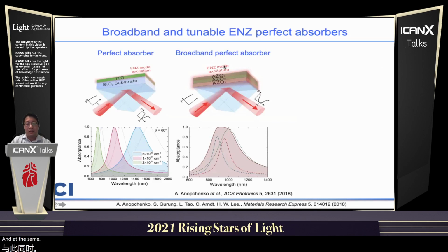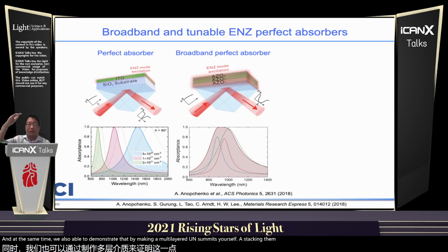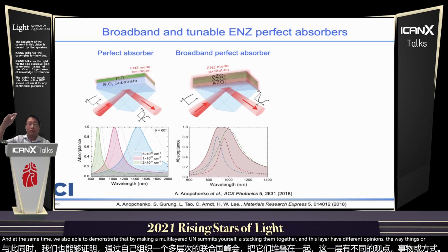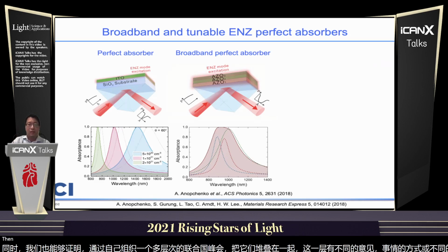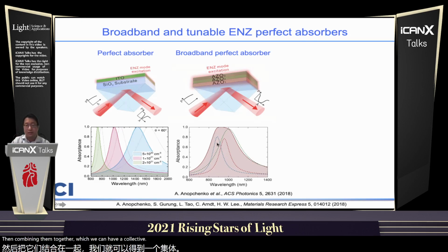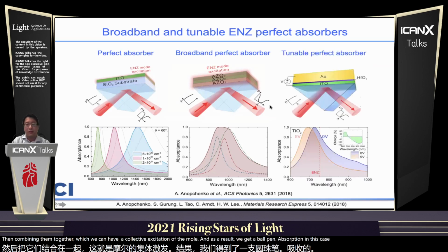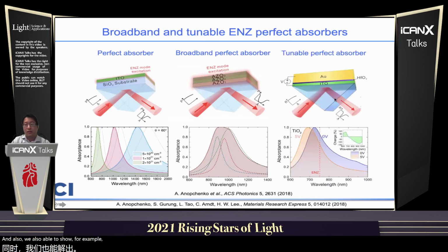And at the same time, we're also able to demonstrate by making a multi-layer ENZ material. So stacking them together, and each layer has a different ENZ wavelength or different carrier concentration. And combining them together, we actually can have a collective excitation of the mode. As a result, we get a broadband absorption in this case. And we're also able to show, for example, making a tunable absorber based on this. Applying voltage, you can tune the absorption band, with quite a large absorption modulation here. So all of this is more or less a linear property of this ENZ optics.